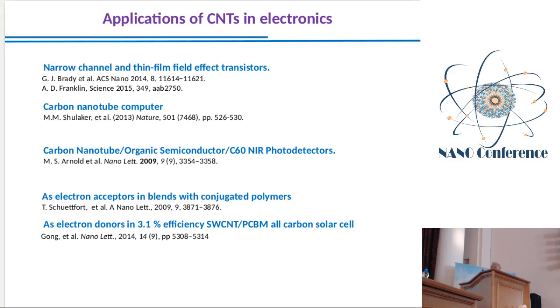Another kind of application is in optoelectronics. For example, carbon nanotubes and organic semiconductor devices, including C60, were used in near-infrared photodetectors, because carbon nanotubes have absorption bands in the near-infrared. Also, these materials were used as electron acceptors in blends with conjugated polymers for organic solar cells. They were used as acceptors and as electron transporters, because carbon nanotubes have very high mobility of charge carriers.